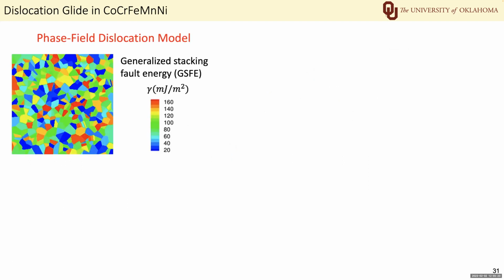So in addition to refractory MPAs, the phase field dislocation model has also been used on a non-refractory MPA. This one is made of cobalt, chromium, iron, manganese, and nickel. So we divide the simulation cell into many regions and assign different generalized stacking fault energies to different regions.